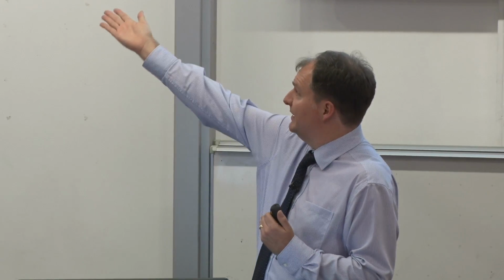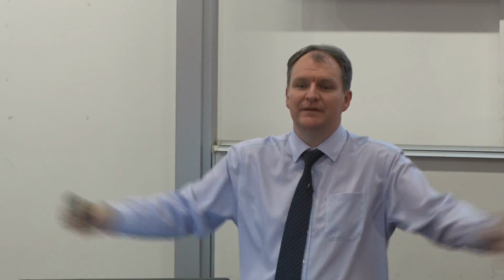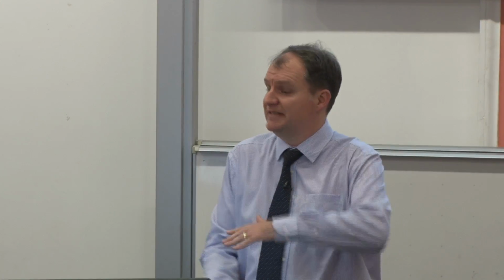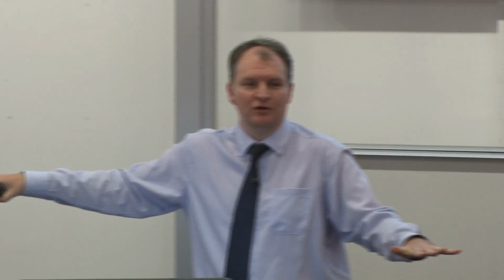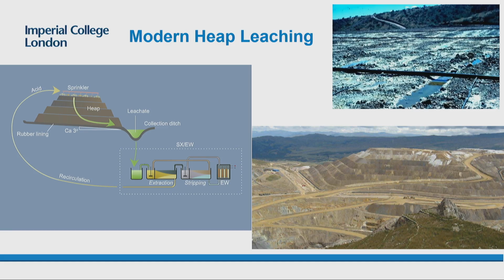Heap leaching works by piling up this material into large piles. You can see some of them at the bottom there. These things can be kilometers long, hundreds of meters wide, tens of meters high. And you just sprinkle acid onto the top of them. It's nearly like a home irrigation system. The pipes are actually very similar. They're just dripper pipes dripping acid onto the top of this heap. This percolates through the heap, dissolving the copper out.